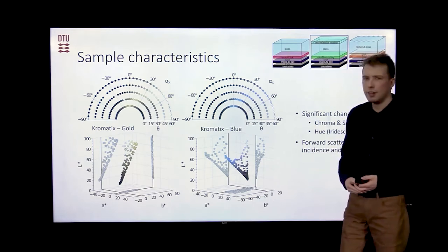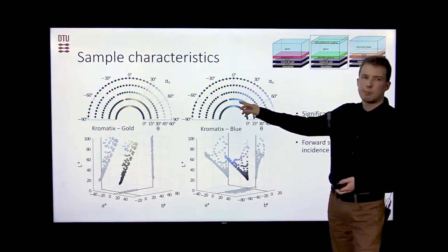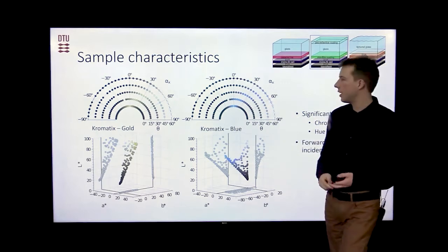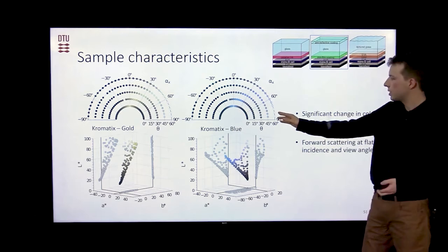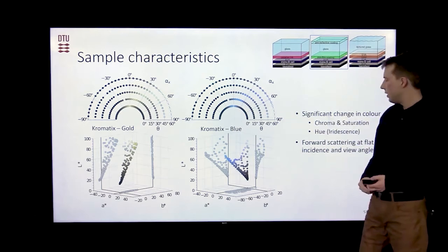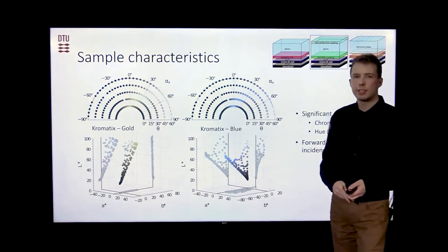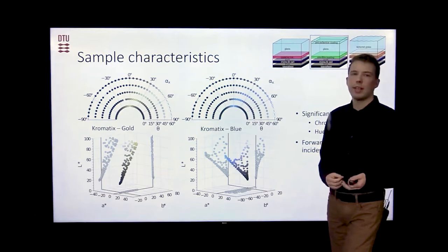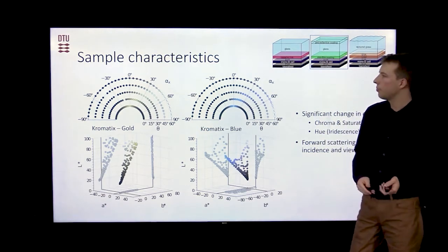which also signifies this change in color, also called iridescence. Regarding the glare, we can see no significant specular reflections from our surface glass, so they are less glaring situations. However, at these very high view angles, we can still see some white points. And these represent forward scattering effects, basically edge bleeding effects, and we cannot discount those completely. So these might cause, in special situations, also discomforting glare.